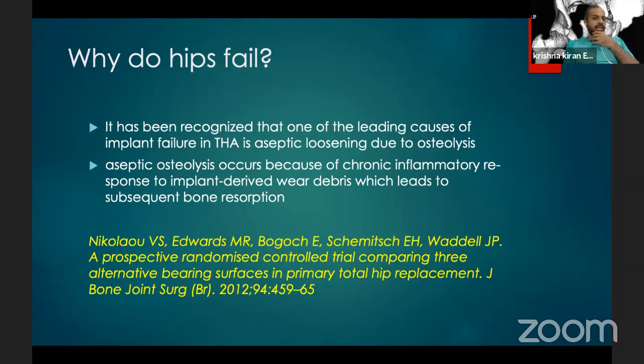And when we look at why hips fail, it has been recognized that one of the leading causes of implant failure in total hip arthroplasty is aseptic loosening due to osteolysis. So aseptic loosening occurs because of chronic inflammatory response to the implant derived wear debris. So we have seen various mechanisms of wear which are possible, and these debris, if they are small enough, if they are biologically active enough, will lead to an inflammatory response through T cells and lead to subsequent bone resorption, which is called osteolysis, and it's an aseptic phenomenon.